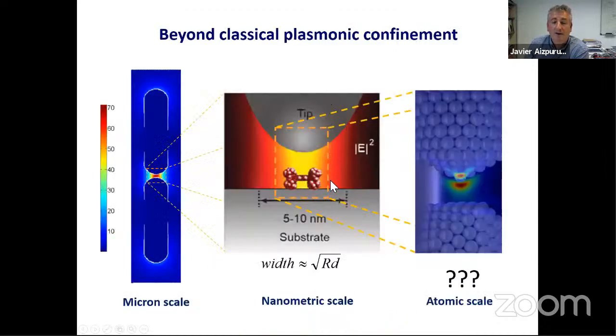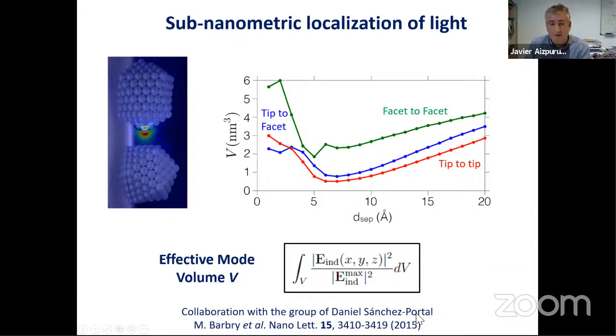And if you remember, I was telling you that the best plasmonic confinement is of the order of 5 to 10 nanometers. There is no way that with this kind of classical or even a smooth Gaussian described local field, we can describe this level of resolution. So there must be something at the sub 10 nanometers scale that traps light to be able to resolve this kind of thing, right? And with the help of the group of Daniel Sanchez Portal here in San Sebastian, who are experts in ab initio calculations, they calculated precisely with time-dependent density functional theory, but in frequency domain, not in time domain, that's perturbative, the response of this kind of junctions at the atomistic level. They put here, for example, a tip metal on a flat metal. This is tip to facet.